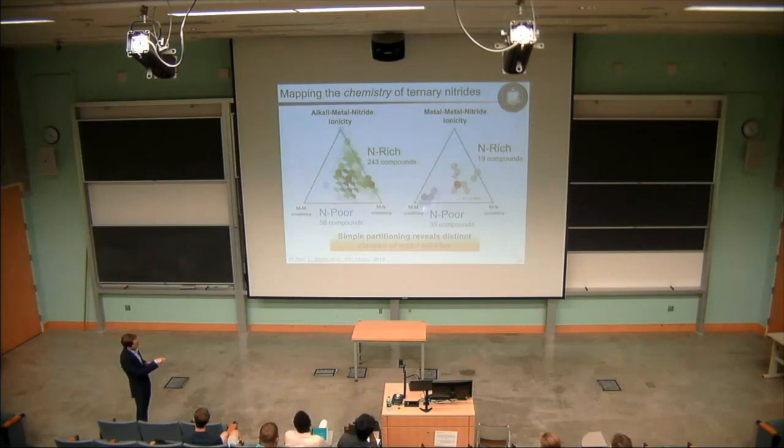And what we find is that these materials are usually nitrogen poor and sit along this metallic corner of the triangle plot, with the unique exception of zinc-containing compounds, which our experimentalists find that when they try to synthesize zinc metal nitrides and magnesium metal nitrides, they see very similar characteristics. So effectively, these zinc-containing compounds are behaving a lot like these classically inductively stabilized ternary metal nitrides.